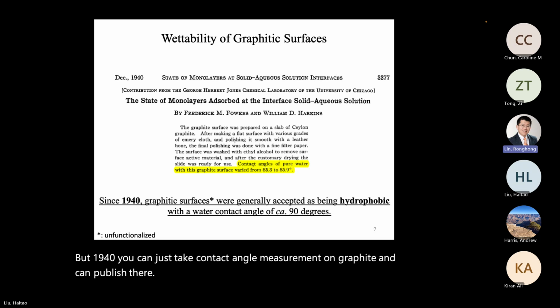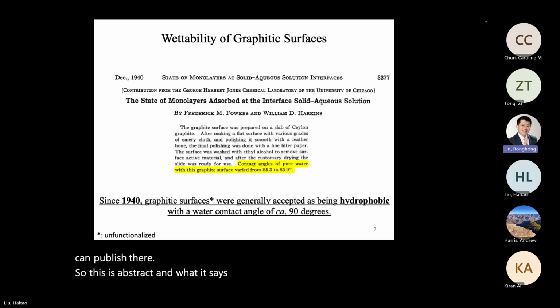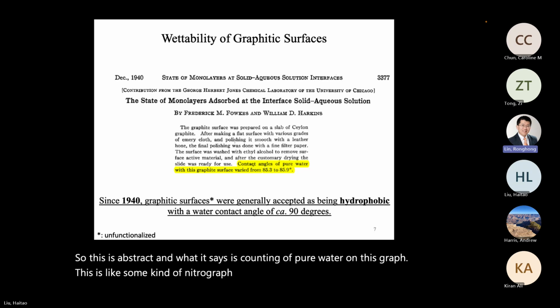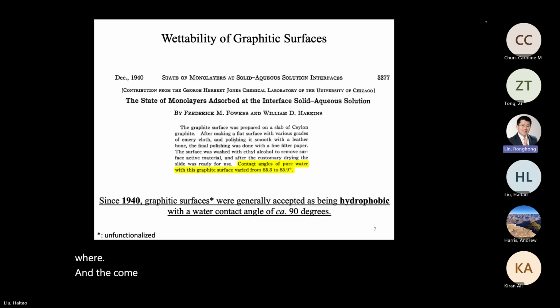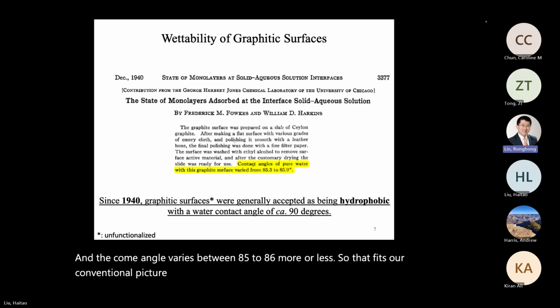So this is the abstract, and what it says is the contact angle of pure water on this graphite. This is some kind of natural graphite from South Asia. I forgot exactly where. And the contact angle varies between 85 to 86, more or less. So that fits our conventional picture that this is a nonpolar material. Nonpolar material doesn't like polar water, so it's a hydrophobic material or surface.